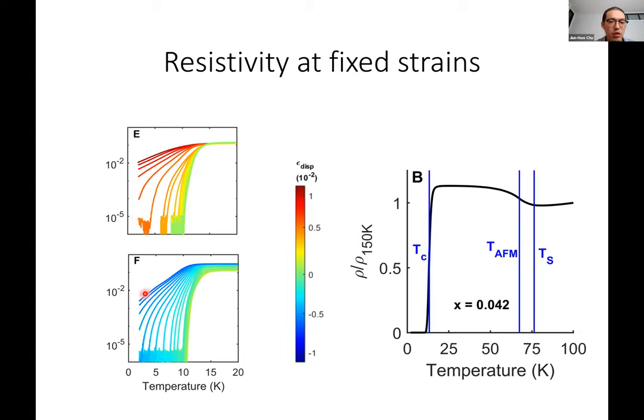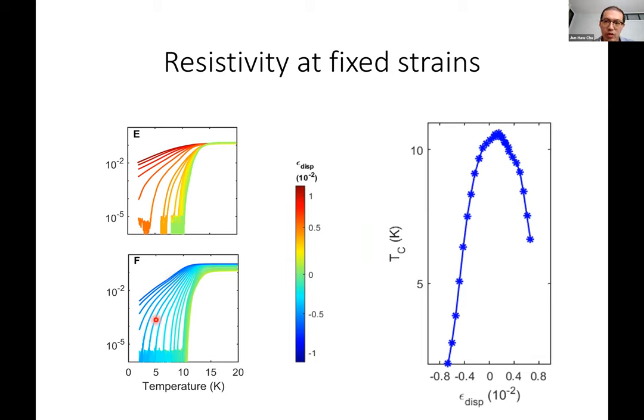In fact, at the most compressive or tensile strain, even though the resistance is dropping almost linearly on a log scale, if you extrapolate this linear curve all the way to zero temperature, it reaches a finite but small value. So in essence, we're actually achieving a metallic state at zero temperature with these strain states, where you have measured finite resistance instead of zero resistance. So you miss, so if we track, I think there's a question.